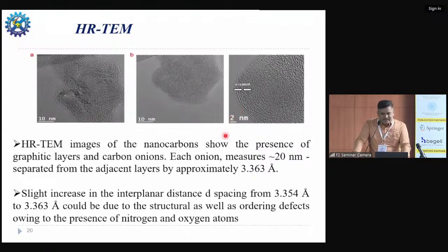And these are the transmission electron microscopic pictures, which show the carbon nano onion kind of structure, where the typical size is about 20 nanometer onions, with an interlayer spacing of about 3.363 Angstrom, which is slightly higher than the typical interlayer distance observed for a graphitic structure, about 3.354 Angstrom. This increase in the interlayer spacing is primarily because of the effects owing to the presence of nitrogen and oxygen atoms, which we just saw.